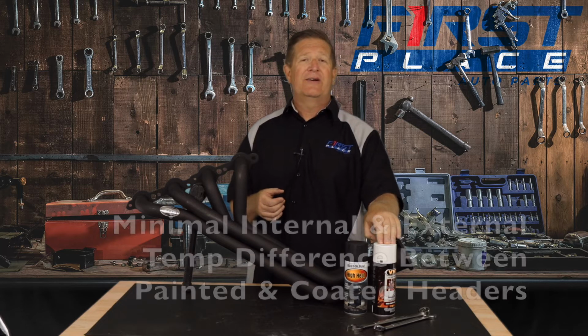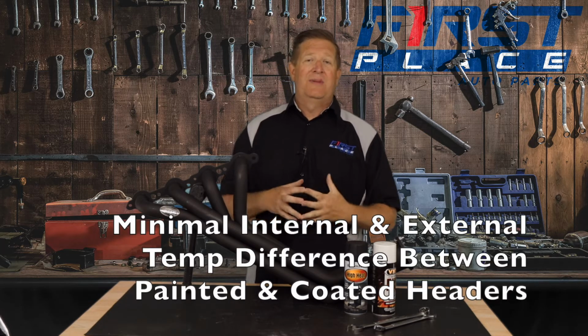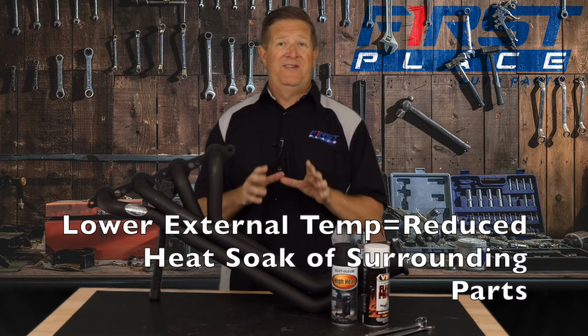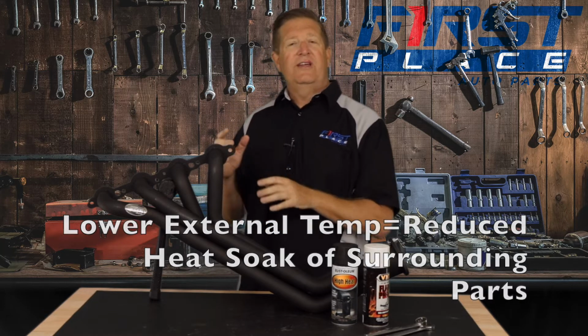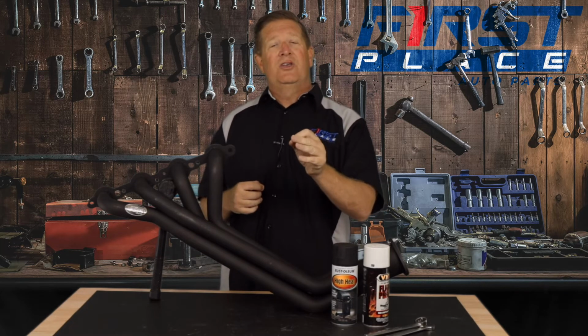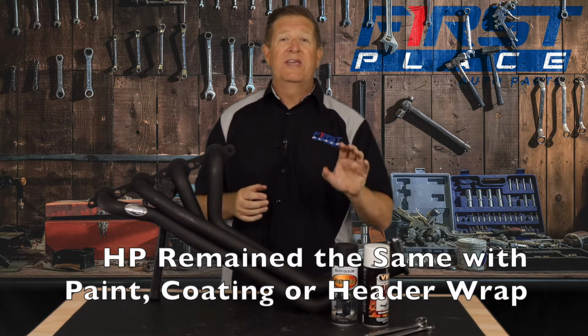In the end, the performance difference, both external and internal, between the painted header and the ceramic coated header was almost nothing. It didn't make much of a difference. The wrapped header, however, reduced external temperatures by 50 degrees. And it also increased the internal or the exhaust gas temperatures, which in theory would increase the scavenging effect of a set of headers. But the reality is, this 350 cubic inch Chevrolet at 6,800, it made 450 horsepower with each one of these coatings. It didn't matter if it was painted, wrapped, or ceramic coated, it made the same horsepower at the end.